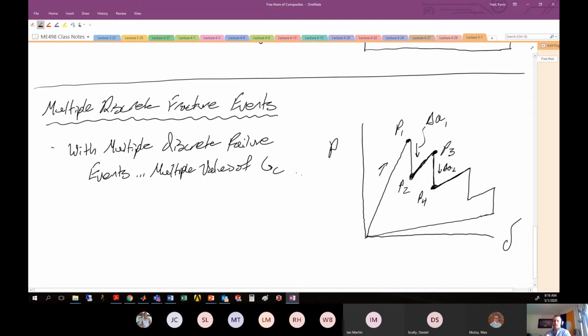All right, this is the general idea. We can define a general location of the load and the displacement so that we can talk more generally about the ith fracture event. So let's do that. Let's say here that generally this displacement and load condition is displacement delta i. And here this is going to be Pi minus. Why do I say Pi minus? Well, that's because that's the load on the sample right before fracture.